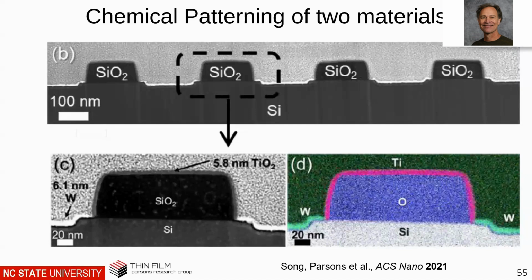You've got to do the top-down and look, because you can just do cross sections, and it's really easy to say, oh yeah, this is perfect. But then when you look top-down, oh, there are dots. So when you see someone publishing cross-section data saying, oh, this is perfect, your alarm should go off.